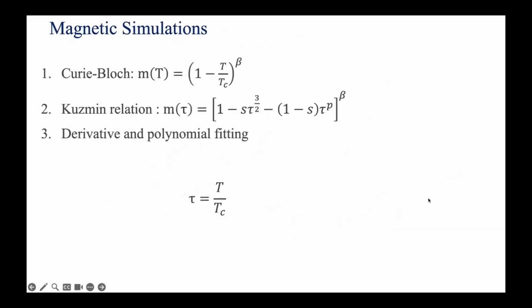One of the softwares that I've used to simulate the magnetic nanoparticles simulates these superparamagnetic nanostructures by atomistic simulation following the Monte Carlo and the Landau-Lifshitz-Gilbert approaches. In this method, the first magnetic property that we want to determine is the Curie temperature, which is the temperature where the magnetic material starts to lose some of its magnetic properties. We make three approximations: we fit using the Curie-Bloch, then the Kuz'min, and then we use the derivative of the polynomial fitting.